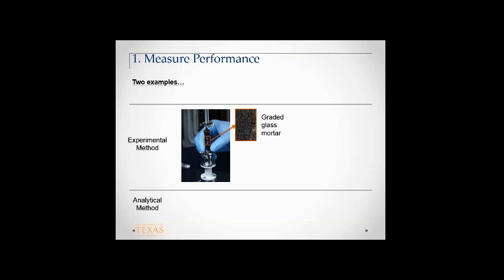And there are techniques that we use, a couple of examples here, to measure these kinds of properties. One is a test on asphalt mortars. Mortar is not the full asphalt mixture, it's not the binder, it is something in between. It is a composite of fine aggregates and the asphalt binder. This is a good length scale because it is more efficient to test and evaluate, takes the aggregate out of the picture. And there's another variation of this where we use glass beads or a gradation of different glass beads, because if you're interested in filler-binder interaction, this is a good system to have. If you're not interested in the filler-binder interaction, you just want to look at the binder performance, you can stick to this kind of system. So there are experimental methods to do that.